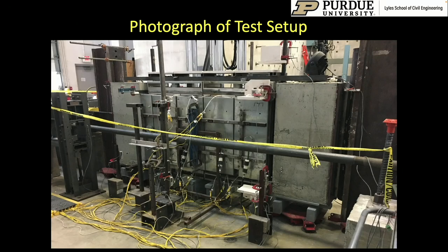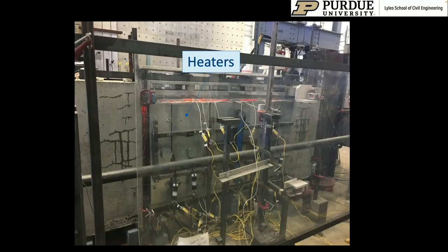A photograph of this test setup in the laboratory is shown here. You're seeing the heaters that are completely enveloping, so you can't really see the wall. It's behind the heaters. And this is a photograph of the experiment in operation. You can see the red hot portions that are subjecting the heaters are heating up the wall specimens. It's almost red hot behind the heaters. You're also seeing some moisture coming out from the concrete as well.